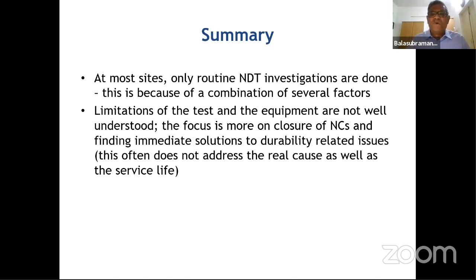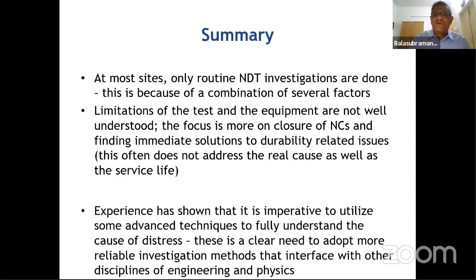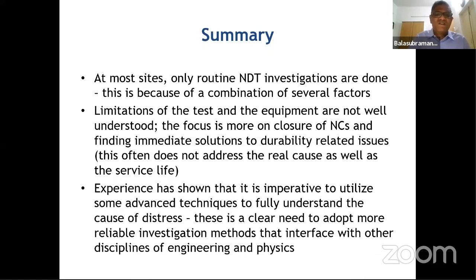The focus is more on closure of NCs and finding immediate solutions to durability related issues, and this often does not address the real cause as well as the service life of the structure. Experience has shown that it is imperative to use some advanced techniques to fully understand the cause of distress. There is a clear need to adopt more reliable investigation methods that interface with other disciplines of engineering and physics. This is very important, but may take a little longer. A lot of people are working, but the confidence level has to be built up so that these things can be taken to the site. As of now, we are doing rebound hammer, UPV, core, half cell, resistivity, powder sample.